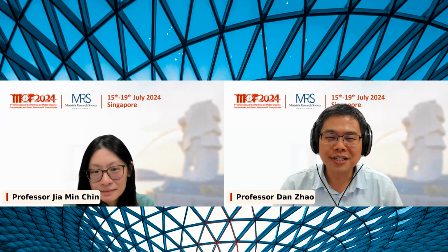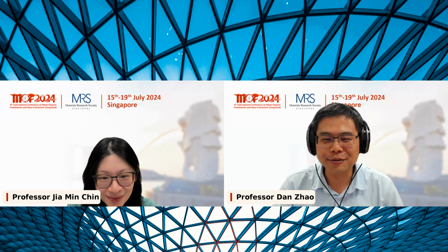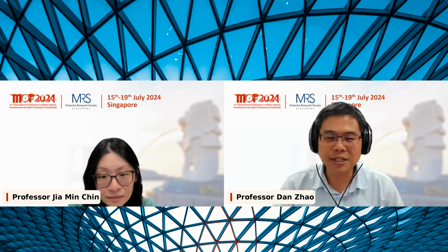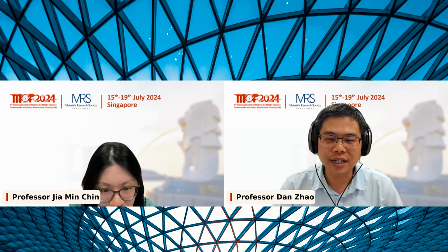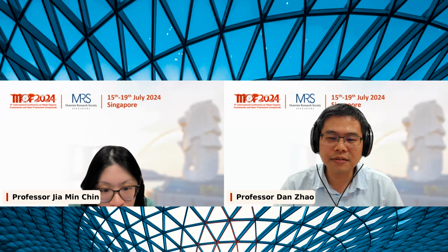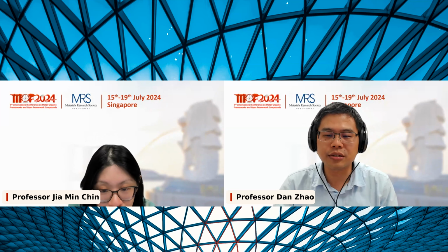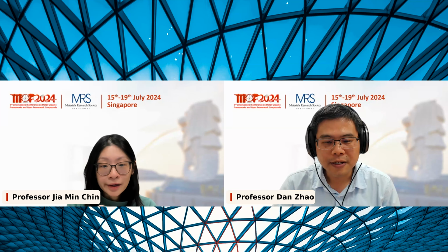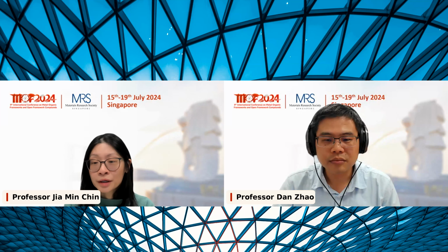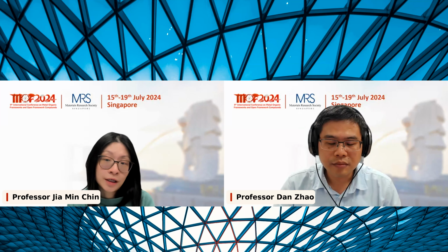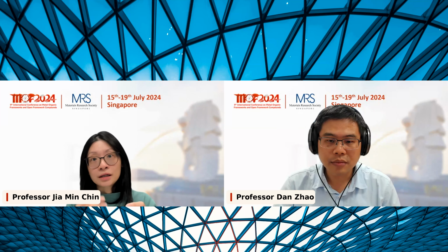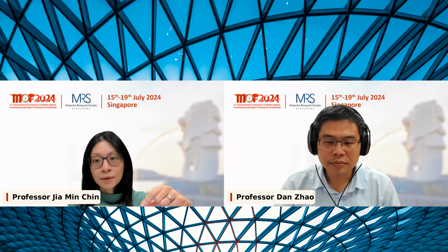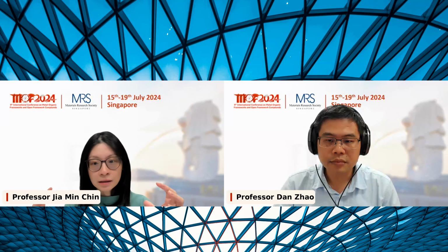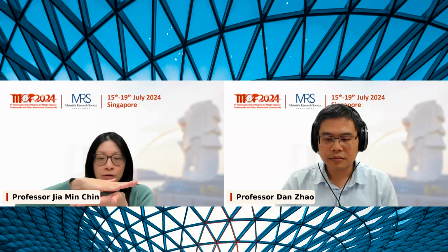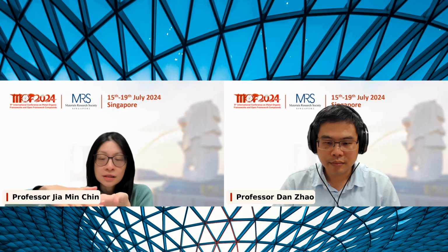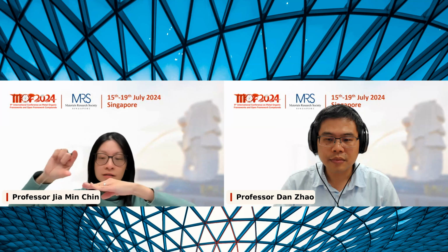Yeah, sure. And Jean is from my group. She asked a question. For the growth of microscale single crystals, the morphology may depend on the growth rates of the different crystal faces, and the preferred orientation is generated. Are there any good methods to control or change the preferred growth orientation of single crystals? Thanks. Yeah, so the classic method is just coordination modulation. In the one example I showed from the Kitagawa group, they showed that if they use a carboxylate linker and they treat this copper NDC DABCO-based MOF, which happens to be a MOF whereby you have this NDC, this dicarboxylate, which grows 2D sheets, and then these 2D sheets have pillars of DABCO in between.